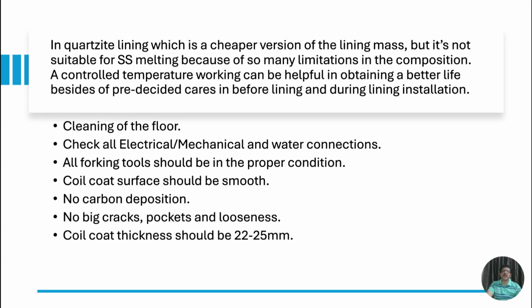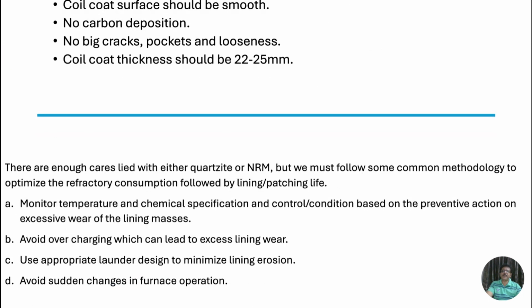A controlled temperature working can be helpful in obtaining a better life, besides pre-decided cares before lining and during lining installation. Clean up the floor, check all electrical, mechanical, and water connections. All forking tools should be in proper condition. Coil coat surface should be smooth. No carbon deposition, no big cracks, pockets, and looseness. Coil coat thicknesses should be 22 to 25 mm.